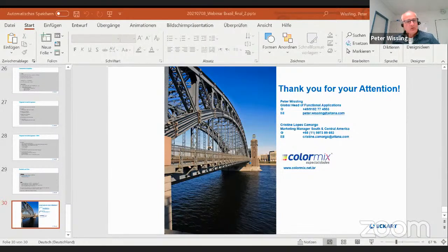First of all, the zinc flakes can be combined with zinc phosphates. That is not a problem. Of course, the zinc flakes will bring in a certain metallic appearance, a grayish metallic appearance, which remains. The yellowing typically occurs, which, however, is related to the binder system that is used. So the typical combination of zinc flake and zinc phosphates with epoxy resins display a yellowing effect, which is, however, coming from the epoxy system. There are various epoxy systems available that are less yellowing, but in the end, it is a matter of the resin system that is used.